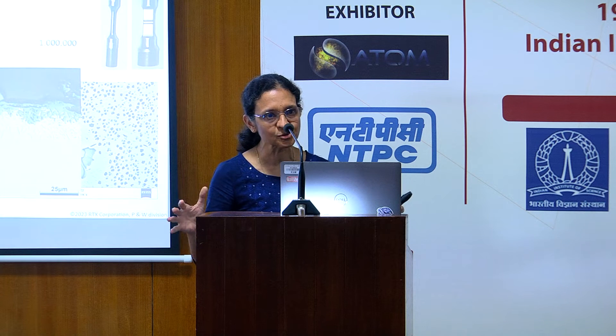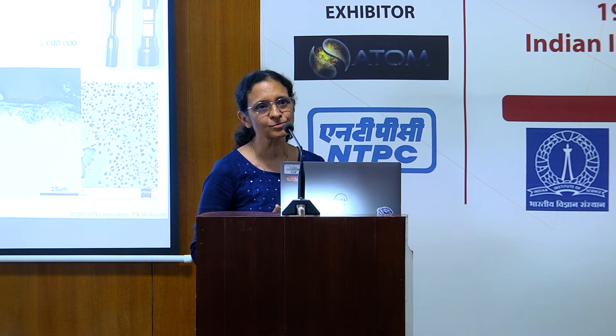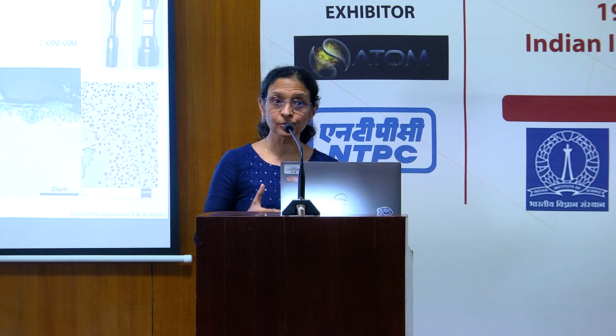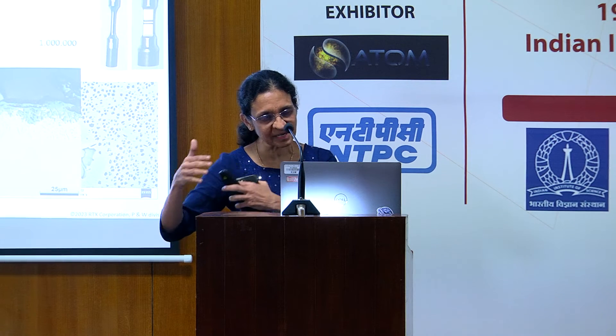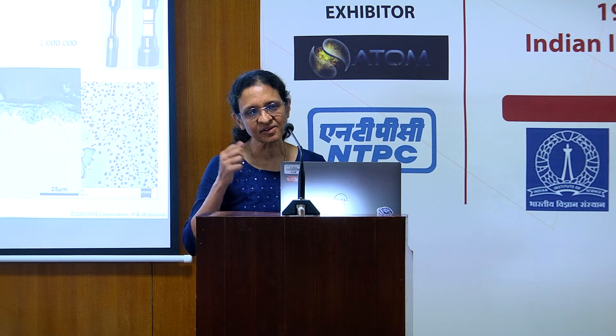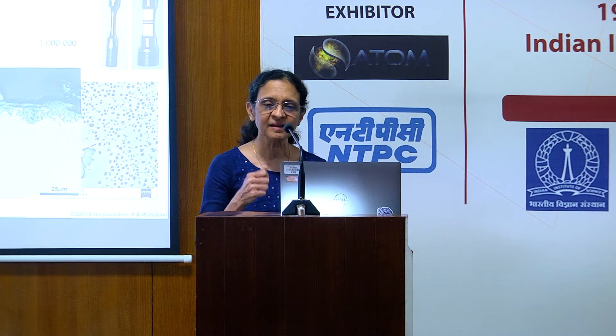We took five different nickel-based superalloys which are actually in the engine — three of them powder metallurgy, one wrought, and one cast — all at temperatures upwards of 700 degrees centigrade. We looked at the reaction kinetics and the nature of hot corrosion occurring. What are the oxides? What are the ceramics that actually form? So that at least as a result of this study, we could tell the repair shop — the MRO — what oxides form, whether nickel oxide, a spinel, or a complex oxide that reacts with sulfur.